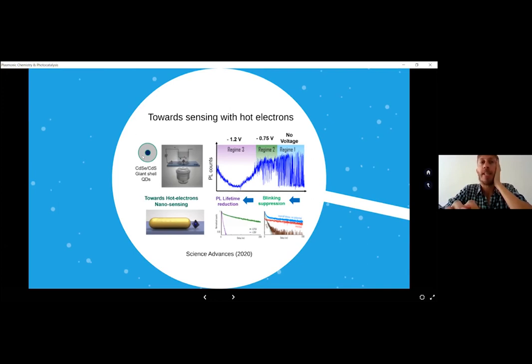We have done that with an electrochemical cell, but our idea is that hot carriers from plasmonic structures can also maybe be transferred to these quantum dots, and we can use the quantum dots as a way to sense the presence of the hot electrons and the transfer of hot electrons in plasmonic structures.